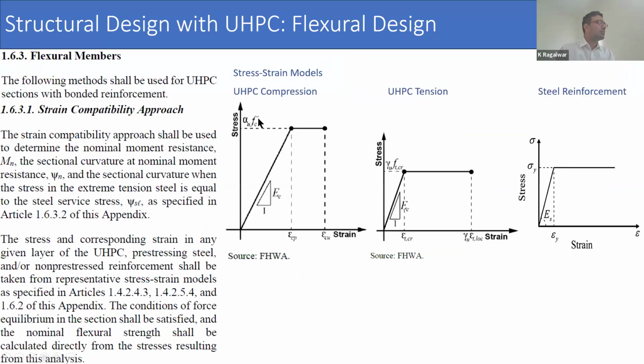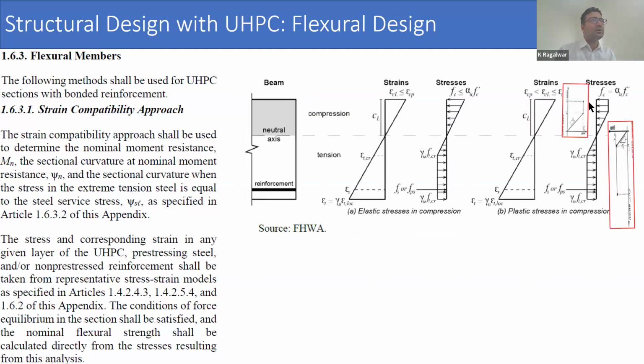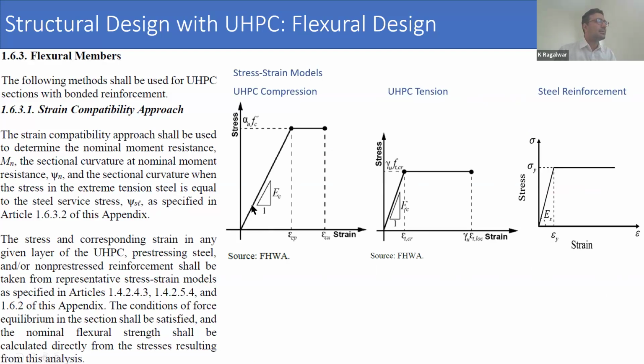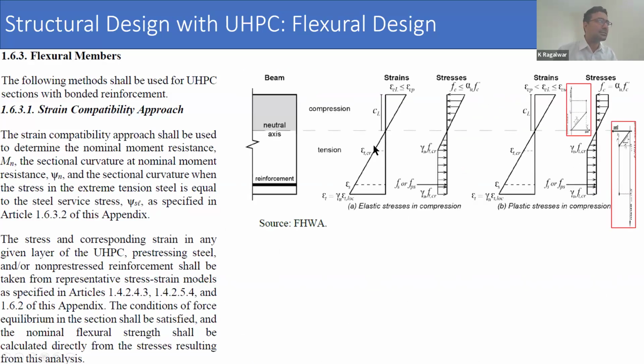So now we have different models: the UHPC compression model, the UHPC tension model, and the steel reinforcement model. These show stress blocks and how we can use them. We know that this bilinear model of compression and tension is used above and below the neutral axis. The first plot here is the elastic stress distribution in the compression block. That means our strain in the extreme compression fiber is lower than the plastic limit, therefore the stresses stay linear. However, with this stress distribution, we see that below the neutral axis, there is a bilinear model. In conventional concrete, this won't be present. You would just have this longer arrow which shows the reinforcement.